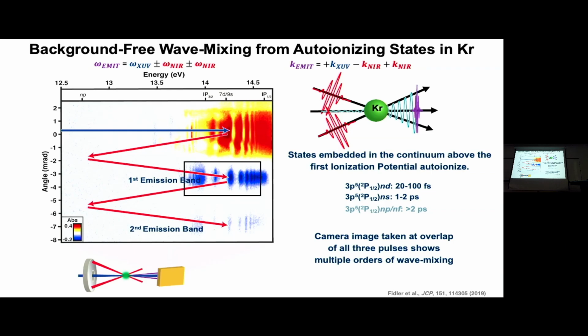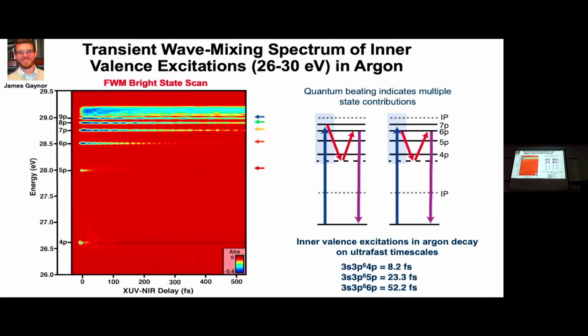And here you can see, this was done in krypton, or I forget, it probably was krypton, that you can get higher orders. So you can have not only four-wave mixing, but six-wave mixing and so on. And the camera image allows you to see all these different orders of wave mixing. When you do this in a gas, like this was done in argon, you can get all these beautiful coherences among electronic states in the gas, and this entire image is background-free, so there's no scattered light or other things in the path. You're seeing only the weak emissions from the four-wave mixing map.